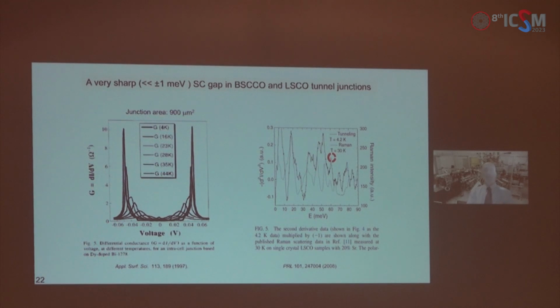We have also done some tunneling experiments ourselves, except in SIS-type heterostructures. And here are a couple of spectacular observations. You can see that these peaks are sharper than 1 milli-electron volt. And note that we are averaging over 1,000 square microns. If the gap varied by 300%, it would have averaged to nothing. We wouldn't be able to see any of these features.